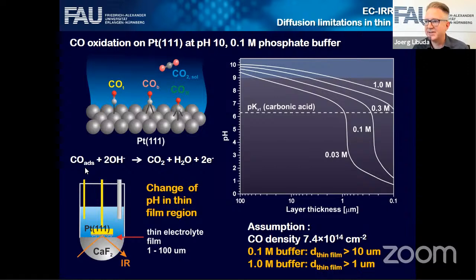However, in this experiment, it's different. Yeah, you have a very small gap. So the volume of the buffer in the gap is very small. Yeah, and also diffusion into this gap can be very slow. And that means that if you do this reaction on a single crystalline surface and you convert the whole monolayer, you may change the pH a lot. Yeah, and you can do a calculation. So this is an example calculation: what would happen if you convert a monolayer of CO in a thin layer of buffer?